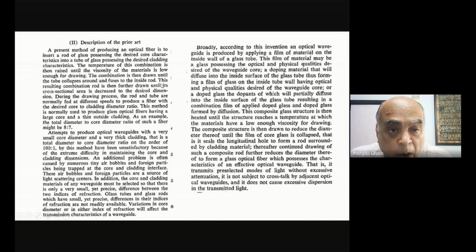The combination is then drawn until the tube collapses around and fuses to the inside rod. So we have taken a tube into which we put the rod. The tube is basically getting softened and collapsing into the rod. That's what is happening. This resulting combination rod is then further drawn until its cross-sectional area is decreased to the desired dimension. During the drawing process, the rod and tube are normally fed at different speeds to produce a fiber with the desired core to cladding diameter ratio. So you can pull the tube and the rod at different rates, and you can alter the ratio between the cladding and the core.